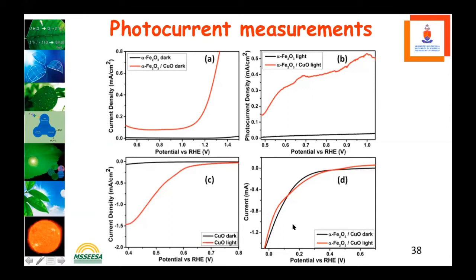And then look at C with the copper oxide alone, you can see the difference between the small values that you find in copper oxide alone under dark and under light, and then look at the heterojunction. In the heterojunction, both under dark and under light are very close to each other, which shows that we have to do better work on both.